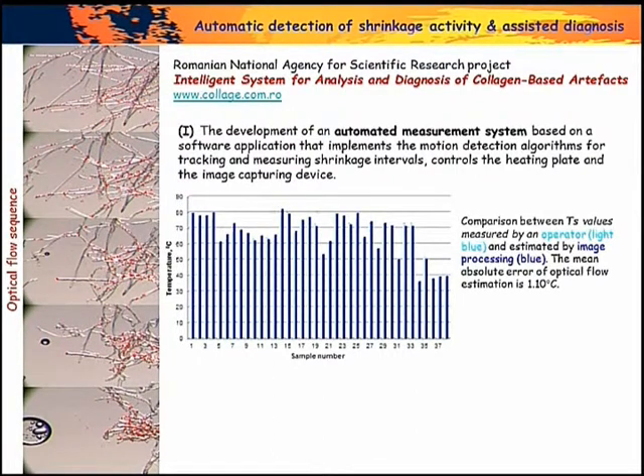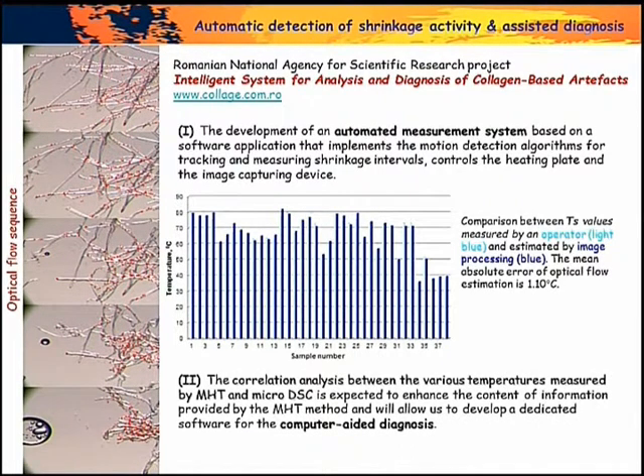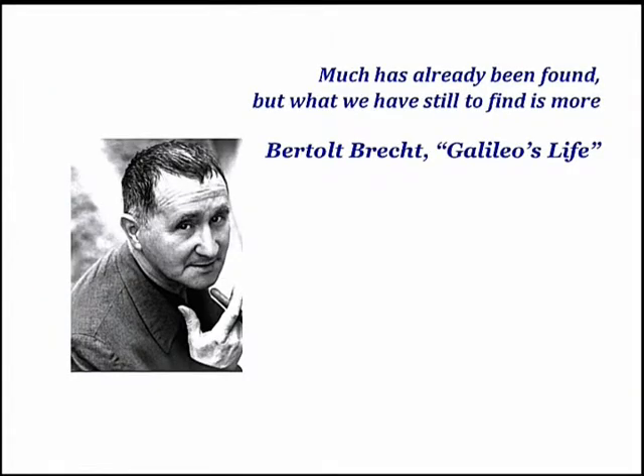These are preliminary results, a comparison between the shrinkage temperature measured by an operator and by image processing. We obtained an absolute error of optical flow estimation of about 1.1 degrees Celsius, and the error of an operator measurement is about 2-3 degrees Celsius. The correlation analysis between the various temperatures measured by MHT and micro-DSC is expected to enhance the content of information provided by the MHT and will allow us to develop dedicated software for computer-aided diagnosis. Thank you very much.